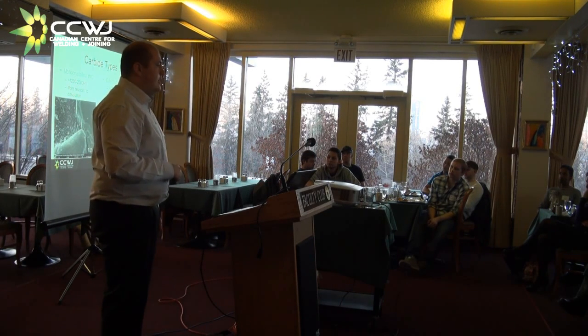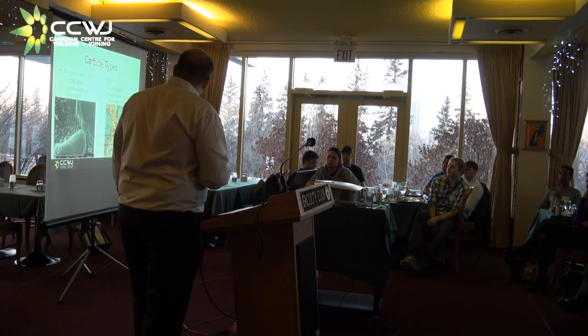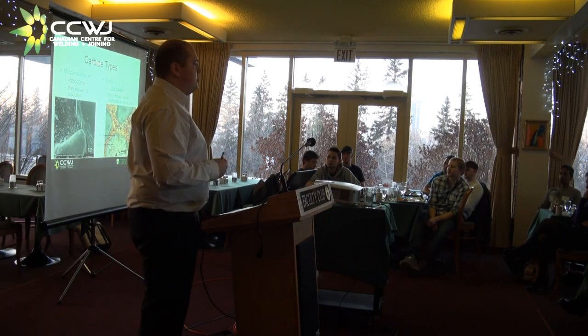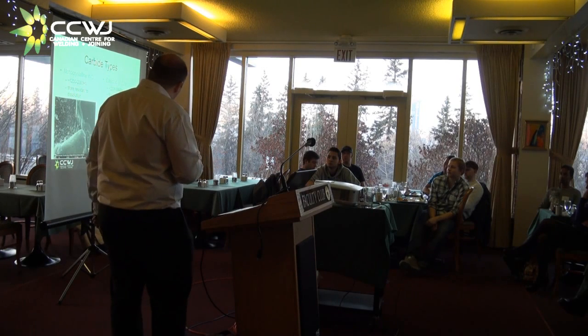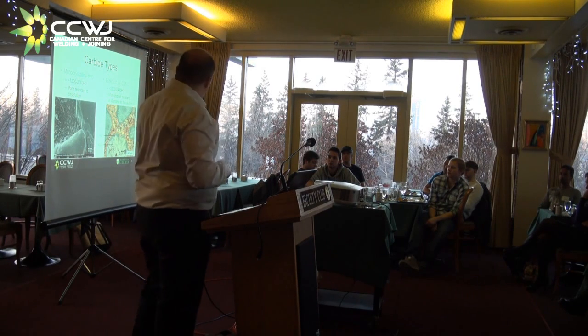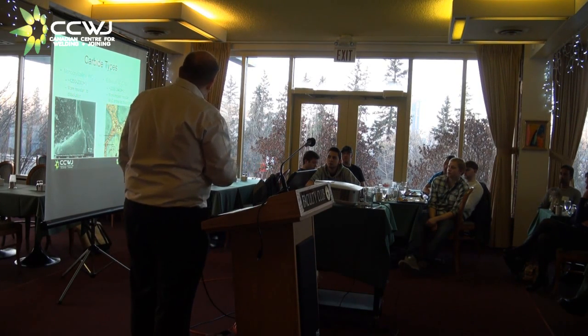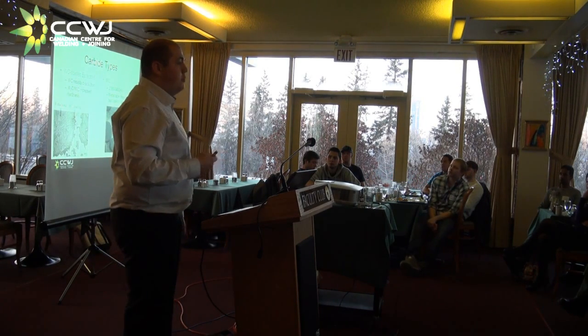On the flip side of things, we have these eutectic W2C WC carbides. They're a little bit harder. The problem with the W2C phase, and that can be seen as this lighter phase right here, is it's very prone to dissolution. So you'll often see either kind of like this shark fin dissolving pattern here where the W2C is preferentially eaten away, or we'll see kind of these halos or dissolution bands around these carbides. And that's evident of overheating or an incorrect weld procedure. And this will give us poor wear results, especially in an erosion-corrosion scenario when there's a wet fluid and there's corrosion issues.